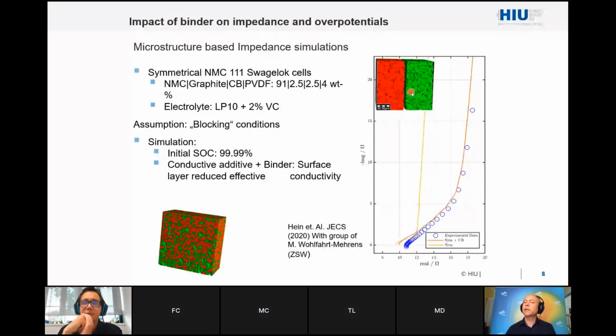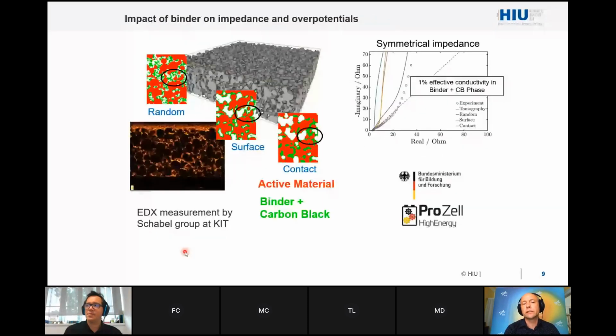And if you simulate impedance spectroscopy from microstructural simulation, we see that we get nearly a blocking behavior, what you would expect from a blocking configuration. What you see in experiments are these circles here, and you see that there is some kind of diffusional regime, and then you enter into the blocking regime. And what we realized is that we can capture this only by including the binder distribution in the electrode. And what was even more astonishing, it mattered quite a bit how we distributed the binder in the electrode. Therefore, the simulations shown in the first part are so important.